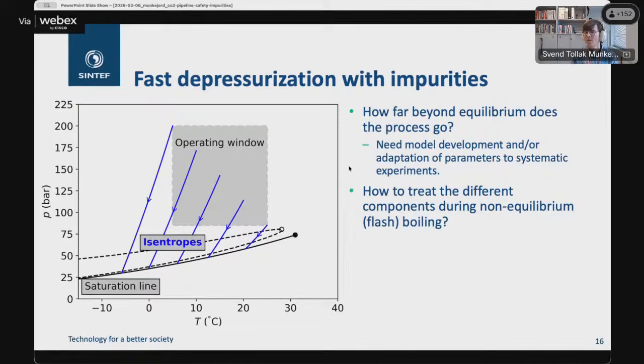Now, for impurities, there are some open questions that we should investigate more. In particular, how far beyond equilibrium does the process go? Because it's so fast that, for instance, in this isentrope here, in reality, it wouldn't stop at the saturation, but go a bit below. And in order to find this out, we need model development and also adaptation of parameters by comparing with systematic experiments, and this remains to be done. Also, an open question is, when we want to calculate what happens in this 2-phase region here, how do we treat the different components when there is no equilibrium? This is also a question I haven't seen the answer to.